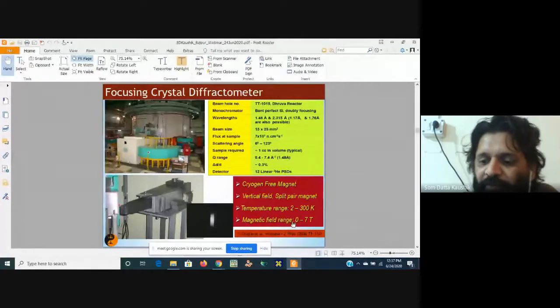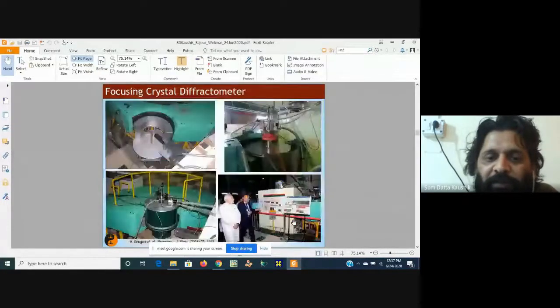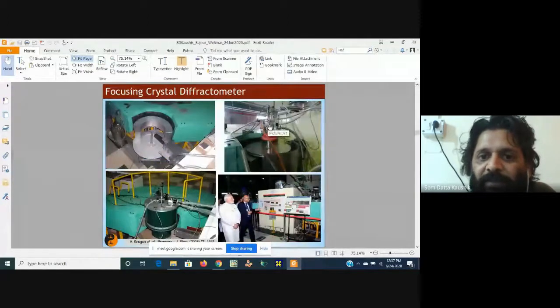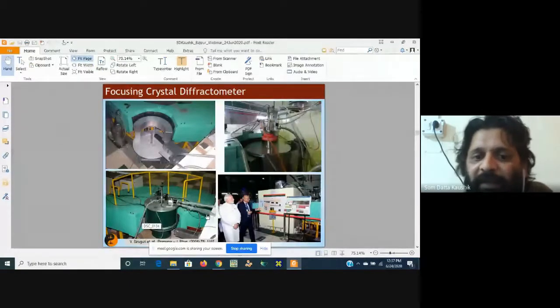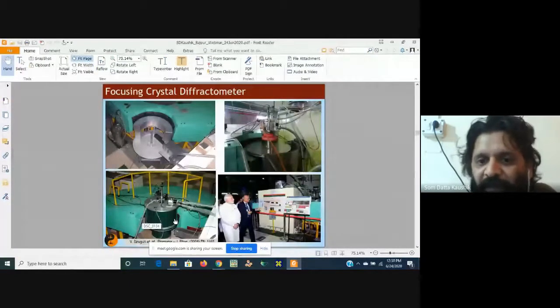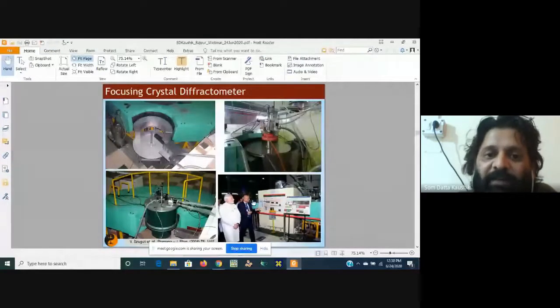So we have two instruments for that. One instrument is a simple CCR, a cryogen free closed cycle refrigerator. We can carry out a neutron diffraction experiment from say 2 Kelvin to 300 Kelvin. Similarly, we have another system, which is a 7 Tesla magnet. We can go down to 1.6 Kelvin and up to 300 Kelvin, and we can apply a field up to 7 Tesla. And this is some recent visit of PM in our diffractometer.